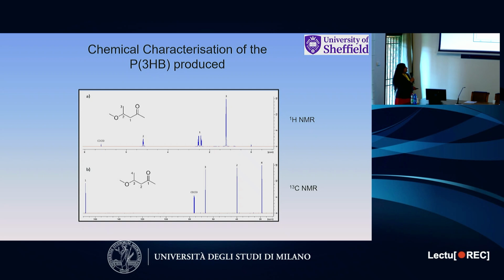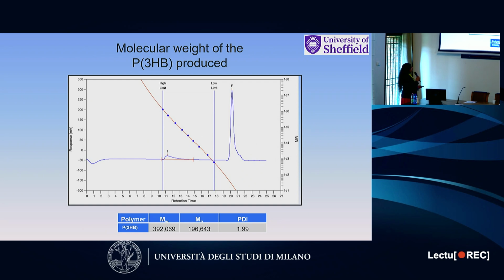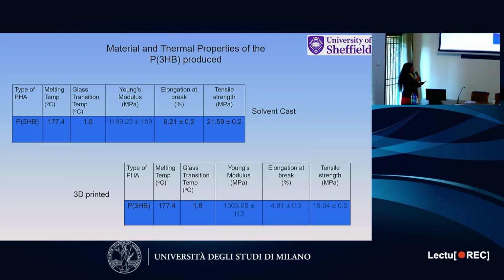So this is, of course, making sure that I isolate this polymer from bacteria, making sure I get exactly the same polymer every single time. I do an NMR, proton and C13. I also look at GPC, gel permeation chromatography, to ensure that the molecular weight is also the same, because that's very crucial. So this, you can see, is quite a high molecular weight polymer, and the PDI is about 1.99, which is quite good, I think.